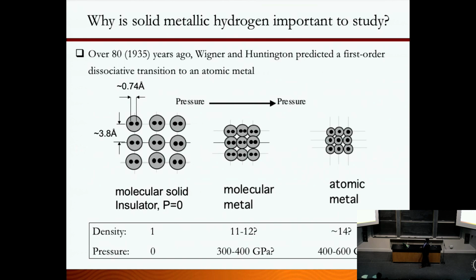Okay. So why is hydrogen so important? As in the introduction, this has been predicted a long time ago, nearly over 80 years ago. If you subject it to pressure, Wigner and Huntington predicted that it can dissociate and transition to an atomic metal. So if you look here, this is how hydrogen at ambient conditions is an insulator. And the molecules are far apart, roughly around 3.8 angstrom. But as I mentioned here, when I squeeze the material, they get closer and closer. At some point the bands are going to overlap and it goes to an insulator metal transition. It can even dissociate and become a metal, so you don't have bound states.